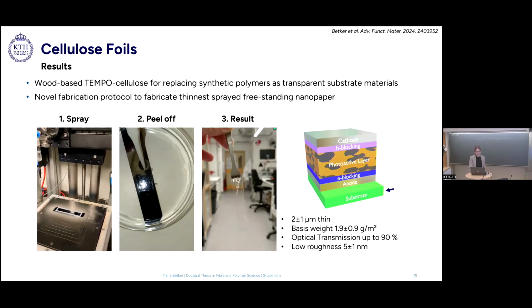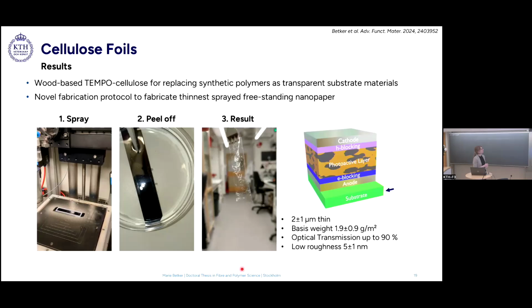And in the third video here, you can see one of my first foils, one of the first results. You can see it's highly transparent, with low haze and high optical transmission. The average thickness of these foils, I gave here as 2 micrometers. However, this is kind of a compromise. I can spray thinner foils, but then it becomes more challenging to peel them off on a large scale without breaking them. So this 2 micrometers was kind of a compromise here.